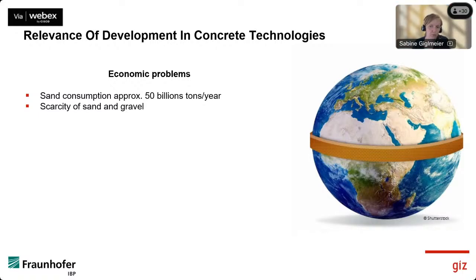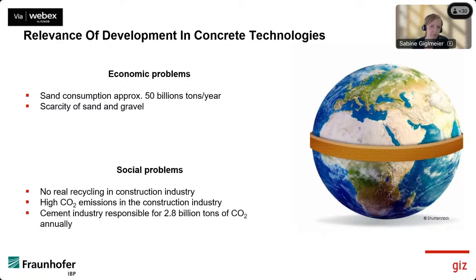The high use of concrete also leads to social problems. The cement industry is responsible for a very high CO2 emission. It's around 2.8 billion tons per year. So we need to reduce this high CO2 emission in the cement industry very soon to reduce climate change. Right now, we do not have a real recycling in the construction industry, so we also produce high amounts of waste. So we need techniques to get back material out of waste.